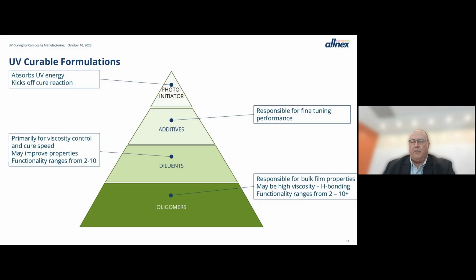The oligomers can be pretty viscous, and so to get it down to an application viscosity, use the diluents. The nice thing is these will react into your system, so there's no volatiles coming off. They can affect properties. They can improve cross-linking and help your properties out that way, but they're mainly used for viscosity control. Not going to go into additives just because there's so many of them, but they're responsible for fine-tuning the performance of your material. And finally, you'll need one or more photoinitiators to absorb the UV energy and kick off the cure reaction.